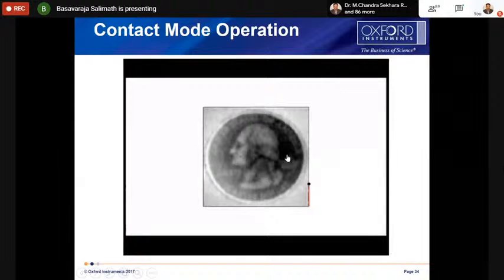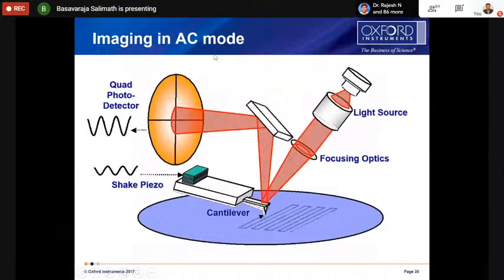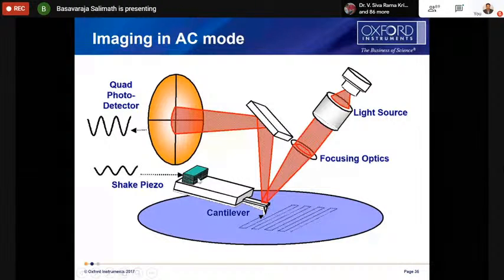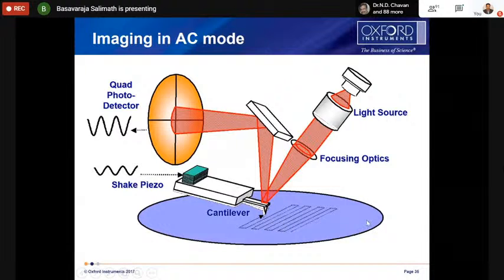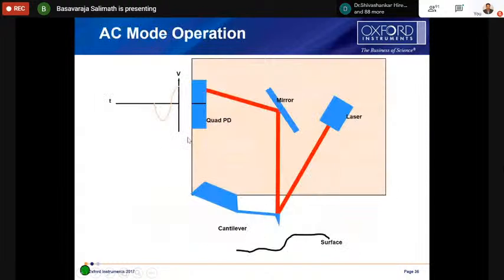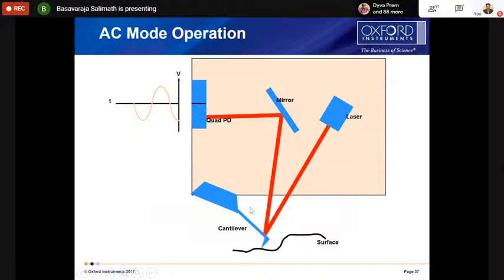In the case of AC mode, it's called tapping mode or semi-contact mode. There is a small shake piezo, and we apply a little bit of biasing to this piezo, then it starts oscillating. This is attached to the cantilever, so the cantilever will also start oscillating. So the tip is oscillating and lightly tapping the surface. When this is oscillating, the laser spot in the photodetector will also be oscillating.